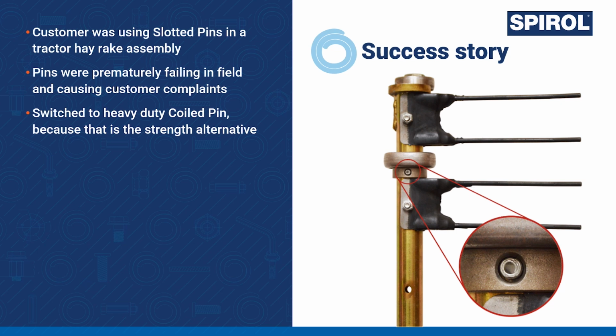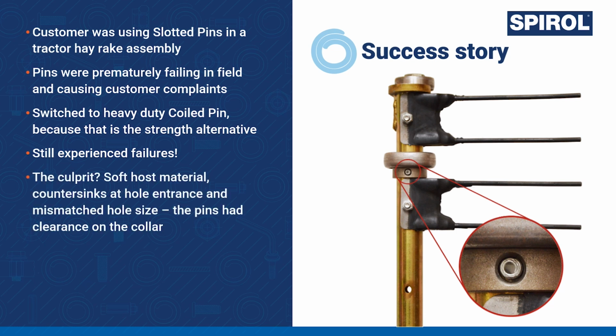A few weeks later, they contacted SPIROL yet again, this time to actually request the application engineering assistance. They said that the heavy-duty coiled spring pin also failed in the application, so they also tried a heat-treated solid pin, thinking that they needed an even stronger pin for the assembly, and that failed too. So upon reviewing the application, SPIROL Engineering quickly learned that the host material in which the pin was used was non-heat-treated cold-rolled steel. The failed assemblies were graciously provided by the customer to us, and were evaluated to determine the root cause of the failures.